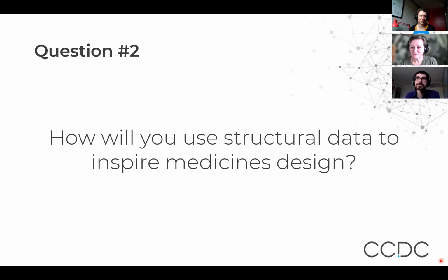So we have another question about electron diffraction, which is a growing field: how represented are ED structures in the CSD? I will say that is absolutely an emerging field. The nice thing about electron diffraction, and I touched upon this in my portion of the seminar, is that the requirements for the comparatively large crystals that you need for single crystal X-ray diffraction are not there for electron diffraction. You can get structural information basically at the nanoscale, which really opens up the opportunities to start getting at structural information for things that are difficult or challenging to crystallize.